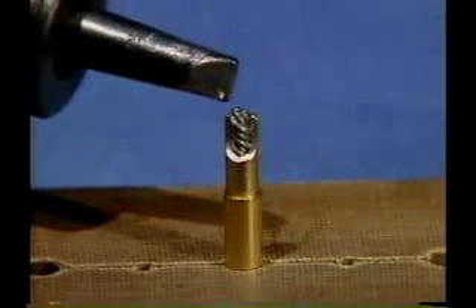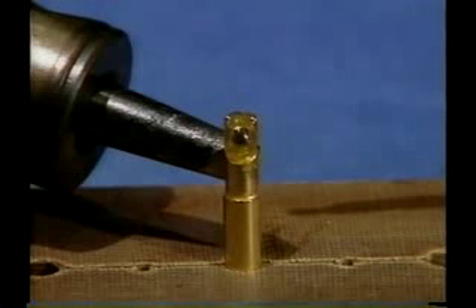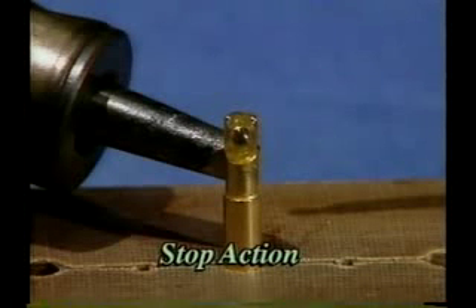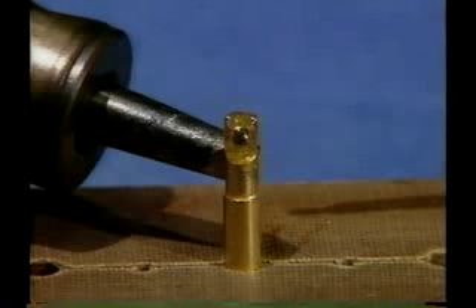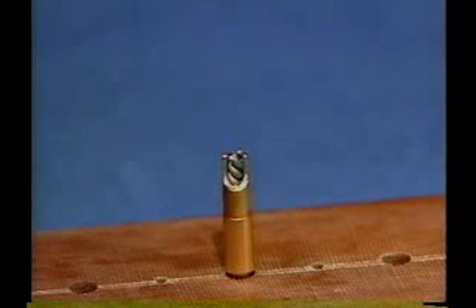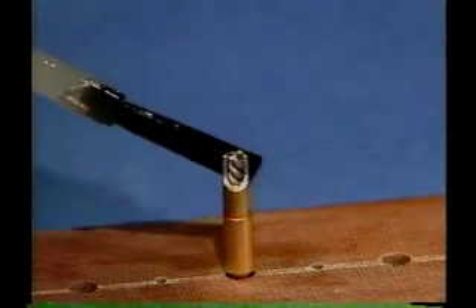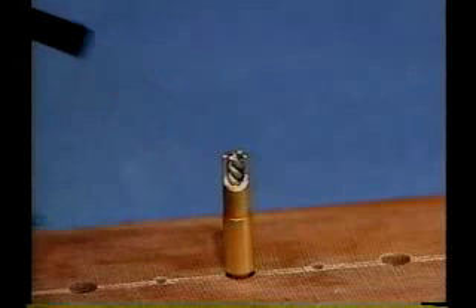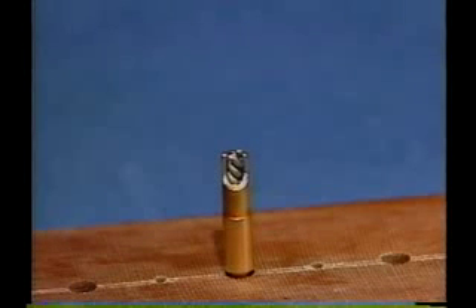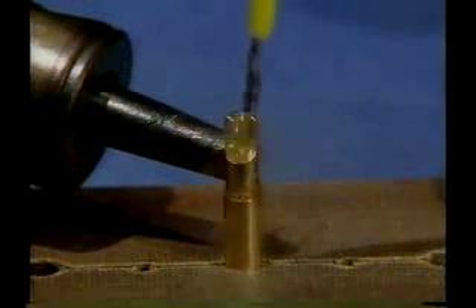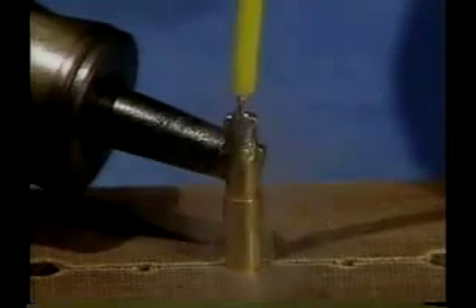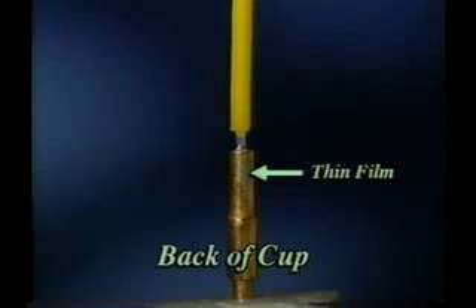The soldering iron is now held on the terminal until solder flow is observed. Notice that a solder heat bridge is not used for this operation because of possible spillage. Another option is to create a heat bridge by using a minimum application of flux on the back of the cup at the point of contact. This will assist in heat transfer and spread out any solder left on the cup from the tip into a thin film, which is acceptable.